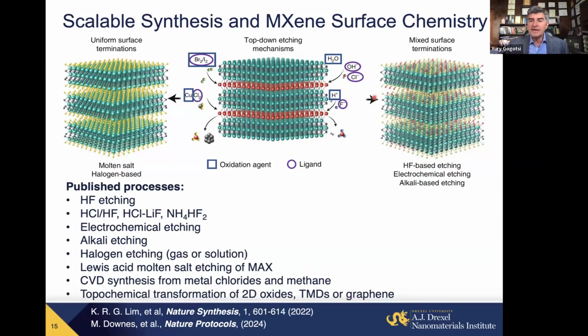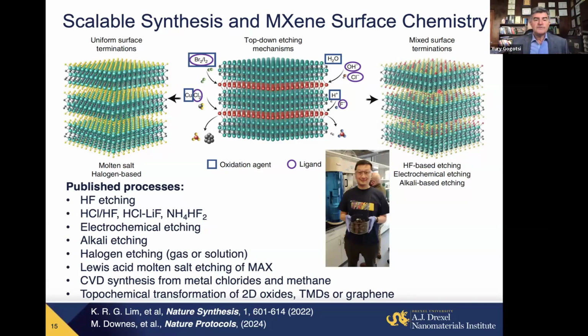But depending on how you make it, for example, in aqueous environment, you will always get oxygen, hydroxyl group and a halogen, for example, fluorine, if you use fluoride salt. If you use halogen etching, molten salt, gaseous, you will end up with a halogen on the surface. So it means different methods will lead to different products. But what is important? All of those synthesis methods are scalable. All of them allow one to produce material in practical quantities.